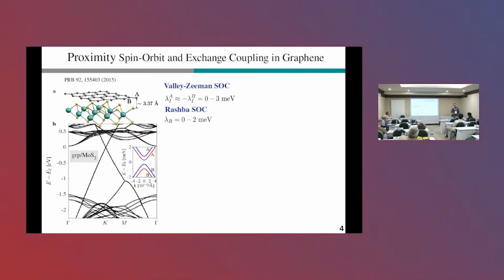Now, one of the spin interactions that can be induced in graphene is the proximity spin-orbit coupling, as we have already heard today. So, for example, if you consider graphene on top of a TMDC, in this particular case MoS2, and you calculate the band structure from first principles, you will find that the two individual dispersions are very nicely preserved due to the weak van der Waals interaction of the monolayers. In particular, the Dirac cone is very nicely preserved within the band gap of the TMDC. However, if you then zoom in to the Dirac states, you will find such a splitting of the bands. This splitting results from the proximity-induced spin-orbit coupling, which is of the valley-Zeeman and Rashba type.